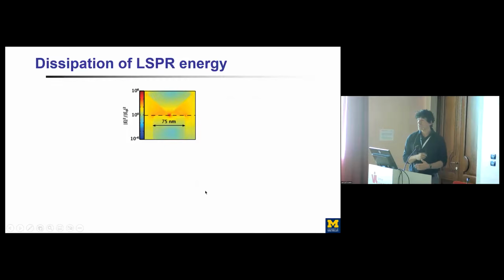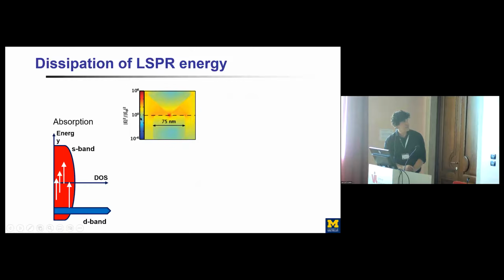So now the question is, how does this energy of light get dissipated? Well, if you have no chemically active environment present in this system, this energy can get dissipated by the excitation of energetic states or electrons and holes in these nanoparticles. So here you can get an absorption process, and this absorption process dominates for smaller nanoparticles of silver, 10 nanometers or less. Or you can have radiative scattering, where you have a scattering of these photons in all directions as they move away from this hot spot.